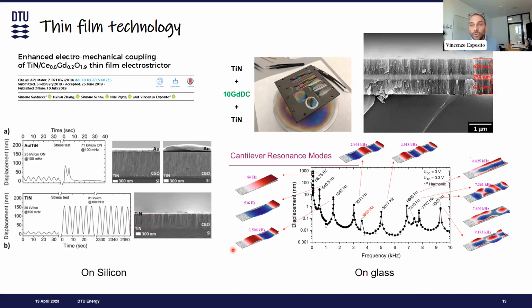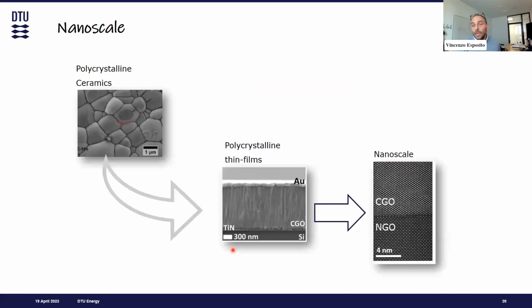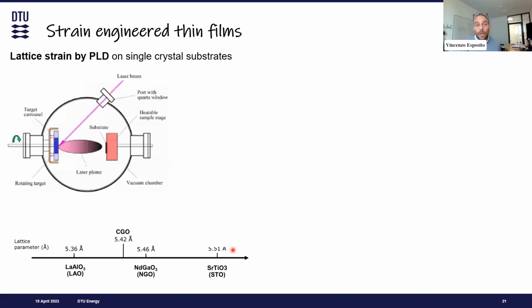And so, using low deposition temperature, for example on glass, we can have a nice electrostrictor, and this is demonstrated here with a cantilever that can resonate at different frequencies. What is nice about this part of the work is that the resonant frequencies are confirmed by COMSOL simulation. So this again is all phenomenological, talking about experiments and results, but there are also some other considerations that we can do more at the theoretical level if we downscale our system to the nanoscale. And I think things get very interesting here.